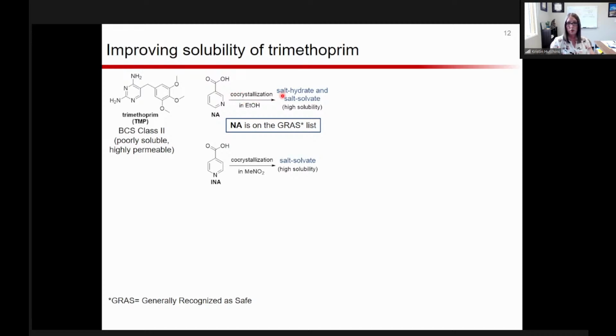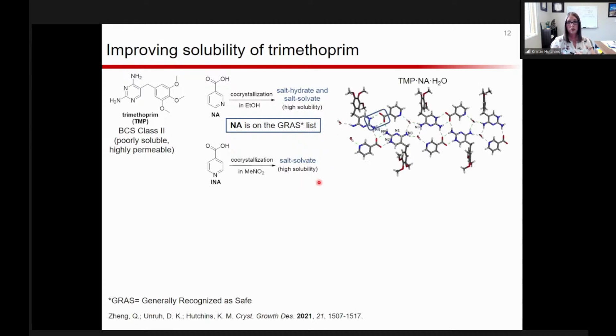Co-crystallization actually gave us two forms. One is a salt hydrate and the other was a salt solvate. The reason these are salt is simply because we have proton transfer from the acid to the base. So it's not neutral. So that's why I've used the word salt. We also used isonicotinic acid, which is just an isomer of the nicotinic acid, so moving the position of the nitrogen on the ring. And in this case, we also got a salt solvate with nitromethane, and all three of these forms exhibited higher solubility than trimethoprim by itself. And so I'm just going to show you the single crystal structures first.